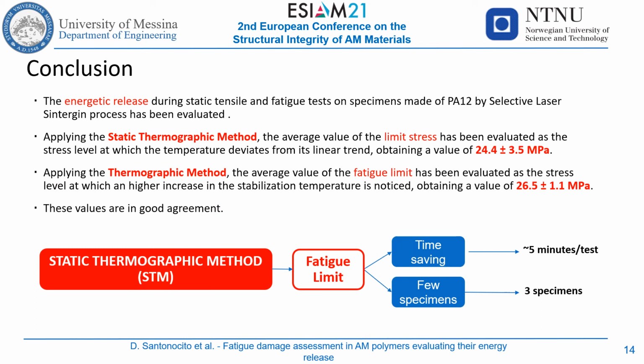In conclusion, in this work, the energy released during static tensile and fatigue tests on specimens made of PA12 by the selective laser sintering process has been evaluated. The infrared camera allowed the application of the static thermographic method and of the thermographic method, monitoring the specimen's surface temperature. By the static thermographic method, the average value of the limit stress has been evaluated as the stress level at which the temperature deviates from its linear trend, obtaining a value of 24.4 MPa.